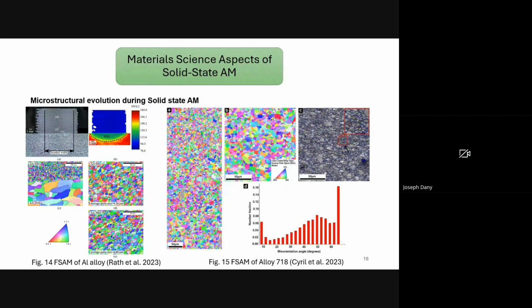In the case of alloy 718, the EBSD image of a friction surfacing deposit clearly highlights a very fine equiaxed structure with a large fraction of high angle grain boundaries. This significant refinement is a direct result of dynamic recrystallization, which occurs under the combined action of severe plastic deformation and frictional heating during the deposition process. Recrystallization in general can occur in two distinct ways. One is static recrystallization, which takes place during annealing after deformation, and the other is dynamic recrystallization, which happens simultaneously with hot deformation. Since friction surfacing subjects the material to very high strain and elevated temperature conditions, the recrystallization observed here is best explained by dynamic recrystallization.